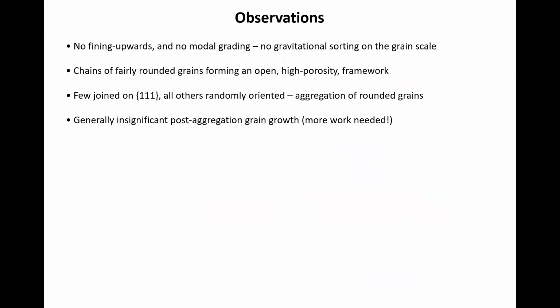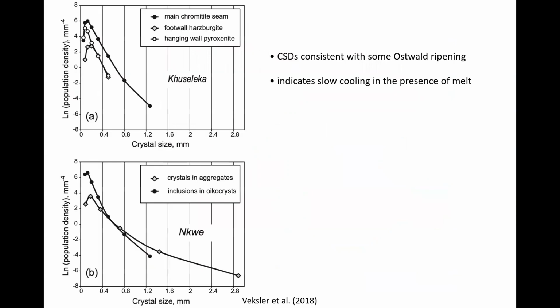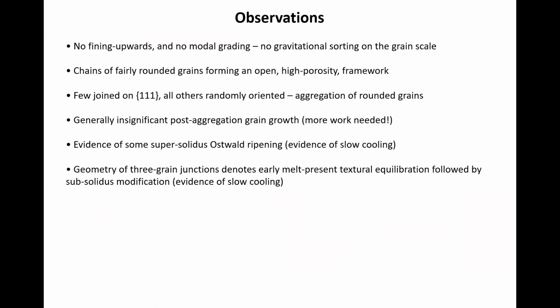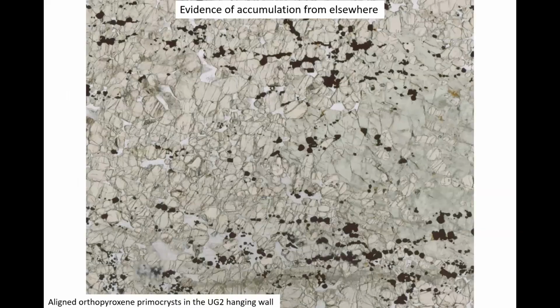Right, so generally insignificant post-aggregation grain growth. We've got some Ostwald ripening, which is Ilya Wechsler's work, which says that once these chains had formed, or once the UG2 had formed, then we do have some Ostwald ripening, loss of small grains, which we know is basically indicative of slow cooling in the melt. So yes, we've done all this already. We've got slow cooling shown by Ostwald ripening, slow cooling demonstrated by textural equilibrium, both with melt present and limited subsolidus equilibration, and I'm just going to rush through this bit.